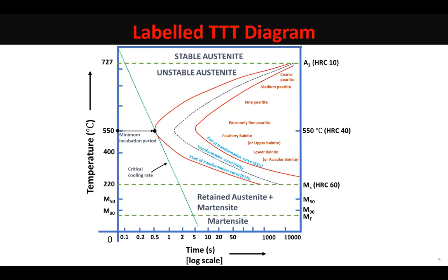The point that I'm trying to make is that whatever grain size the steel was to have has already been fixed through the heating and the holding step. In the triple T diagram, when you talk about the decomposition of austenite, you just talk about the cooling of the steel. So the heating and the holding steps are already locked. That means the grain size which the steel would be showing to you is already fixed.